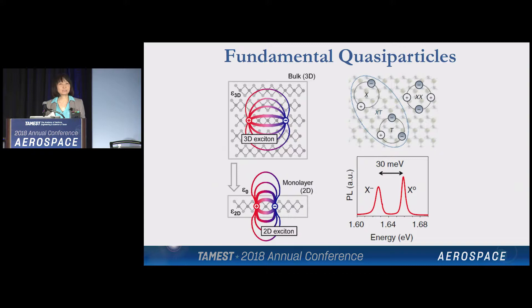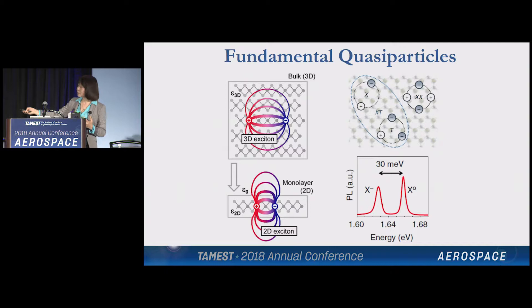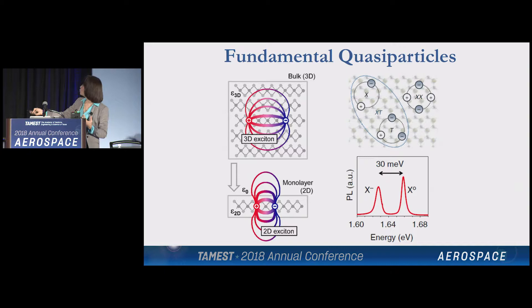What's really responsible for light emission is not a single electron but what we call an electron-hole pair. In a three-dimensional material, these electron-hole pairs have Coulomb forces that are screened by other atoms around them. But when you thin down the material to just one or a few atoms thick, these electric fields get out of the material into the vacuum. That leads to new properties — a whole new zoo of different quasi-particles that give rise to new light-emitting properties.